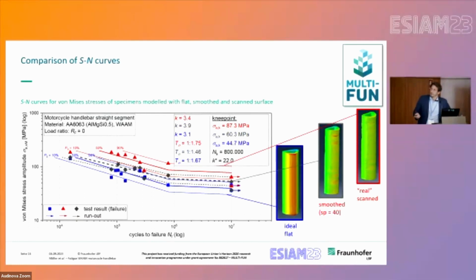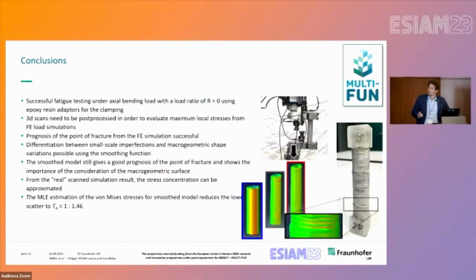But also what we see is that the scatter from the real geometry to the smoothened one decreases from around 1 to 1.7 to 1.46, which is in the range of, for example, welded specimens. From this, just a quick conclusion. So we set up this fatigue testing, which was not straightforward, but worked fine. Finally, in this axial bending mode, we had a good correlation between numerical simulation and fatigue crack location, and then this investigation on the smoothened specimen geometry versus the real scanned specimen geometry, with the results shown before.